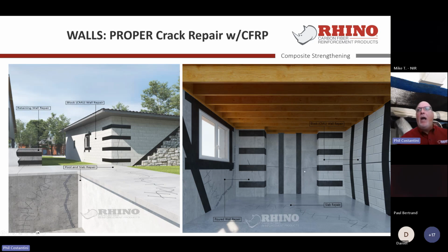So if there's a crack in, let's say, a poured wall or even a block wall, we actually have crack repair kits that are 6-inch wide that would add a lot more strength than spacing out the crack lock. I personally think it's a little bit more cost effective. And most importantly, you're doing a stronger application with a wider bidirectional or unidirectional material, even if the crack is vertical, going all the way down.